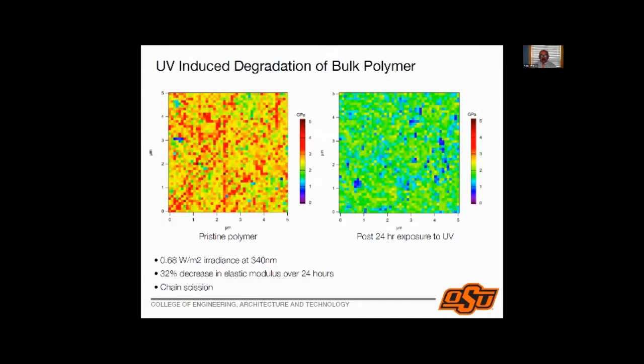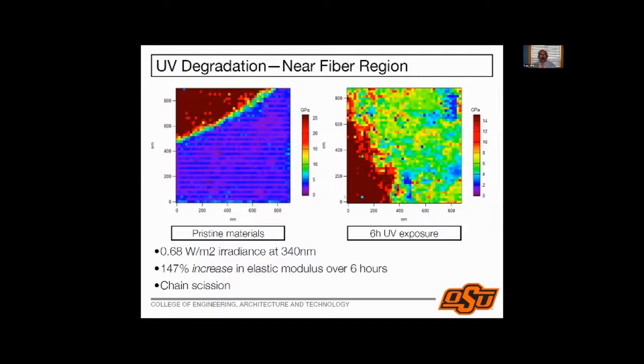Makes perfect sense. If I take a carbon fiber and look at the interface region and I expose it to UV, what we see is, and these are not the same material, these are different materials, because you can't take the same specimen and expose it, but they show the same thing. So here I have the carbon fiber, here I have the matrix, here I have a well-defined interface, and if I take a specimen which has been exposed to UV, I find that the modulus here has now gone up, and the interface is not as clear as the interface earlier.